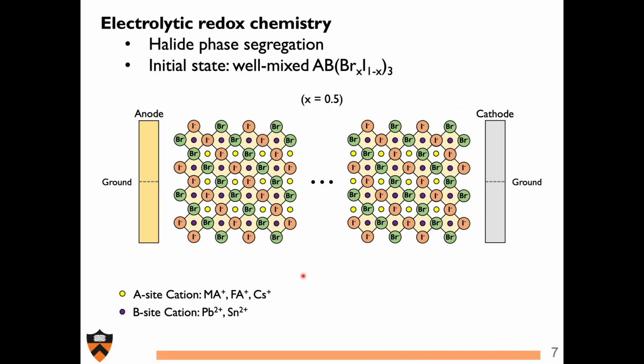So I'm going to show you an example of an iodide redox cycle and something that it does. One thing that we've established in my lab is that iodide oxidation is the first thing that happens, which allows for halide phase separation. So if I have a system that's now a mixture of halides, let's say a mixture of iodide and bromide, the initiating step of redistribution of this lattice is basically to create a lot of vacancies so that stuff can move around. And the thing that creates that vacancy is iodide getting oxidized, leaving the lattice, and now stuff can move about. Ion migration can happen.